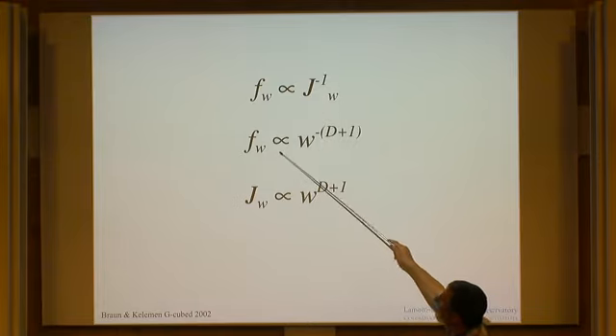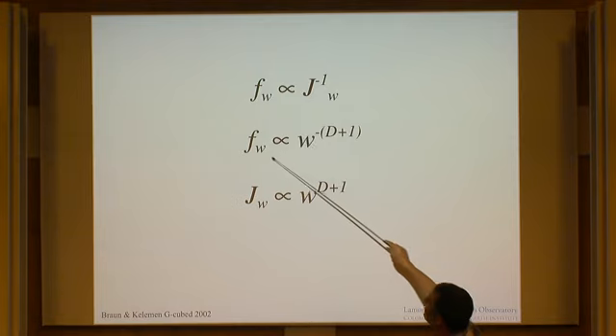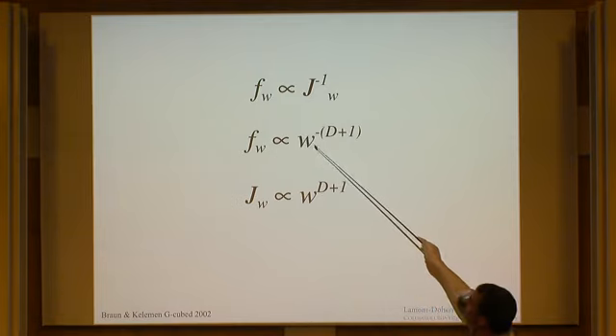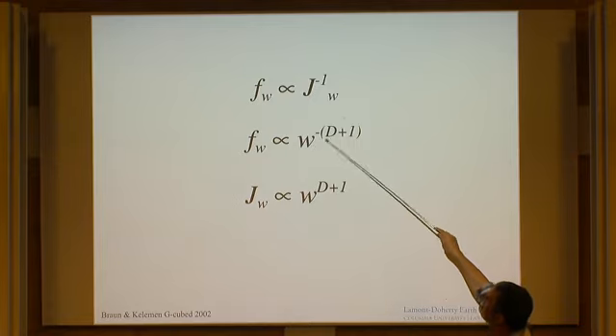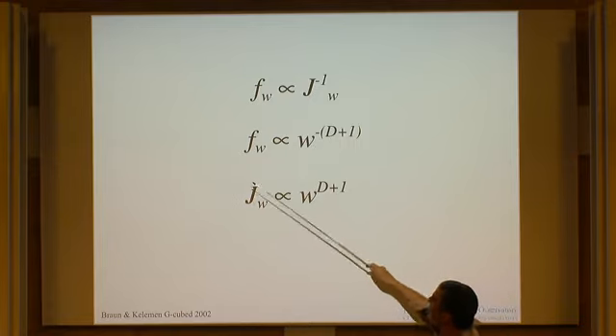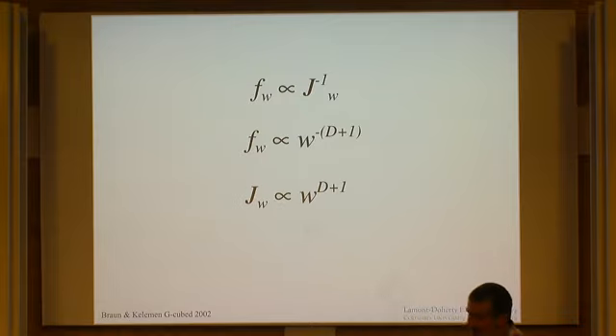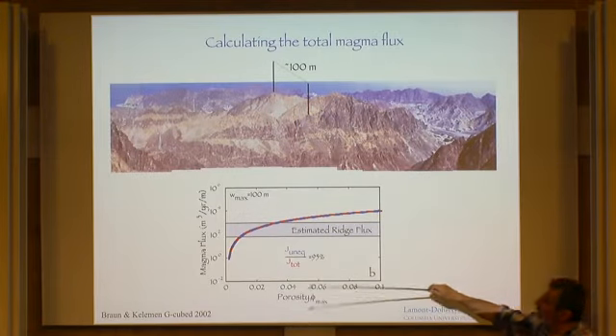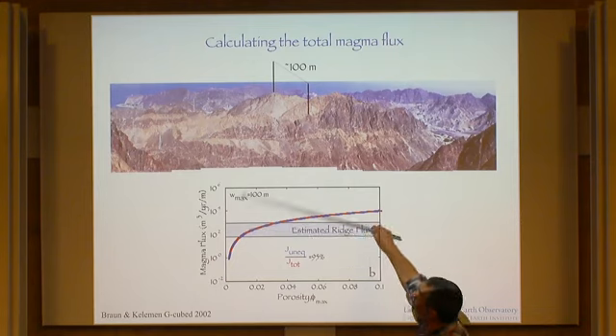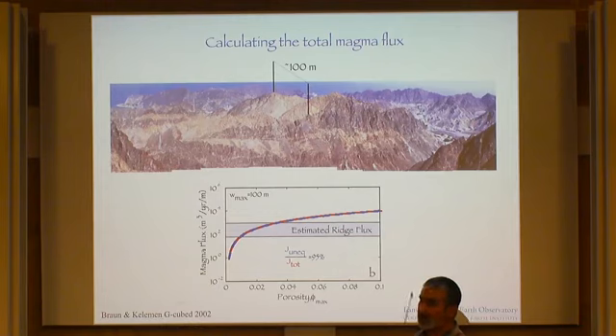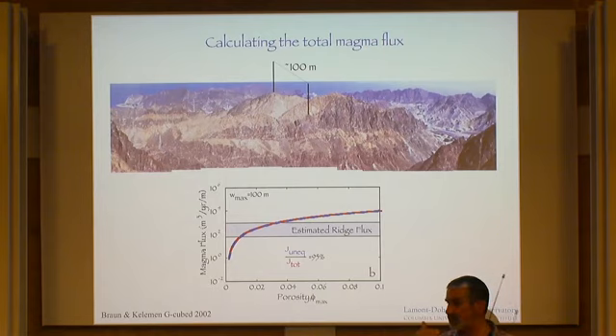And we'll imagine that the frequency is proportional to the width, to the fractal dimension +1, and therefore the flux is related to the width, to the velocities. And when we do that, we can show that there's plenty of melt that can flow through the dunite conduit network alone. We don't need any cracks. Very slow porous flow can satisfy the flux constraints that we know from the rate at which oceanic crust is created above spreading ridges. So there might be cracks, but we don't need them.